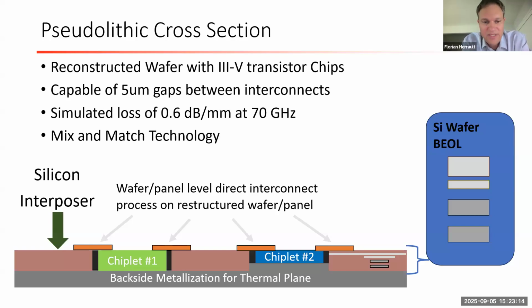And so we have the ability to mix and match thicknesses, as well as interface on the front side, despite the different backend technologies used in the 3-5 suppliers. Maybe you know that some of them may use a BCB encapsulation or an air bridge interconnect, for example, in gold. Just to give you a little more detail, the backend layers on the silicon are 4 layers. That's 2 thick copper and 2 aluminum layers. When we do the CMOS version, we have the ability to have 5 more layers as well.